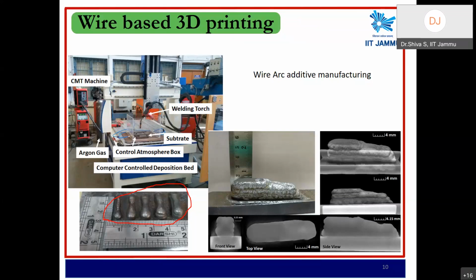In cold metal transfer, the moment the arc gets generated, a short circuit is induced and the arc is almost extinguished. As an effect of that extinguishing arc, excess heat formation can be controlled. Once you control the excess heat in the deposition, this unwanted heat is away from the melt pool. If this unwanted heat is available, it induces secondary phase formation in the alloy. In CMT based cold metal transfer, this problem of secondary phase formation is prevented, eventually avoiding brittle phase and porosity formation within the alloy. This is the magic behind bulk deposition happening successfully.